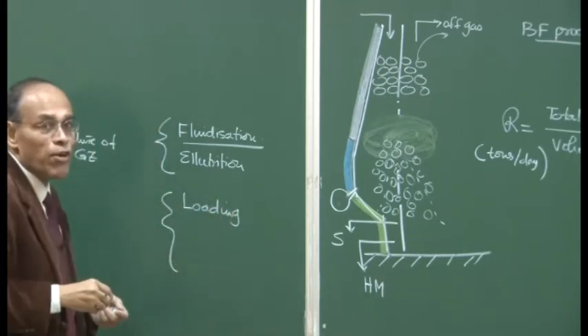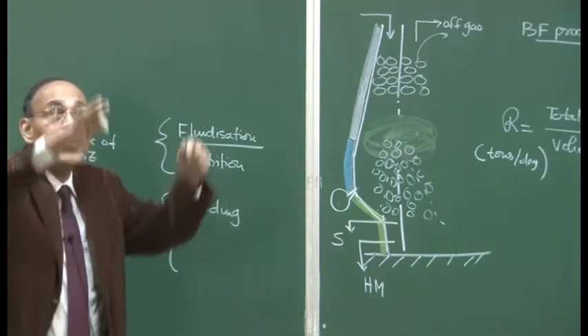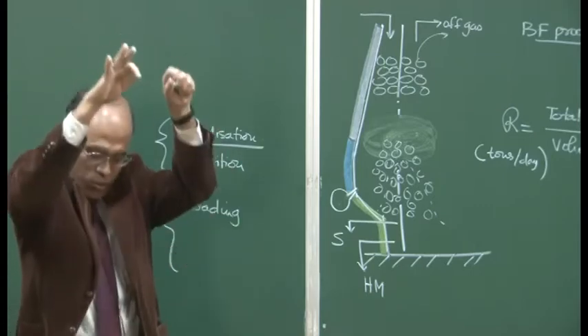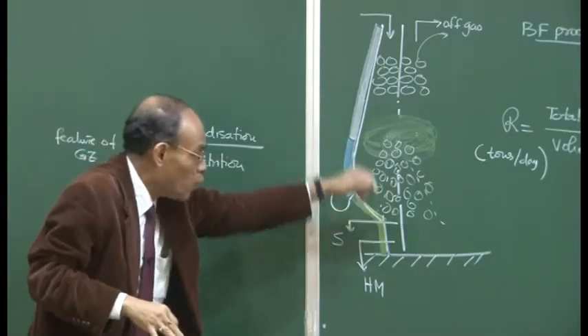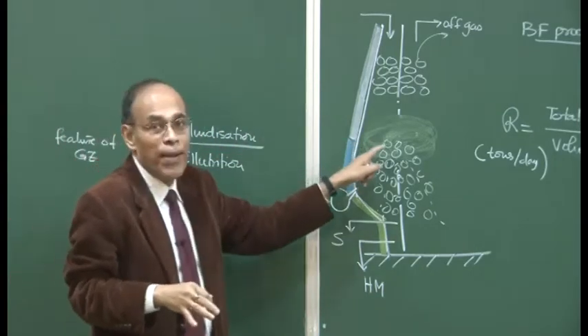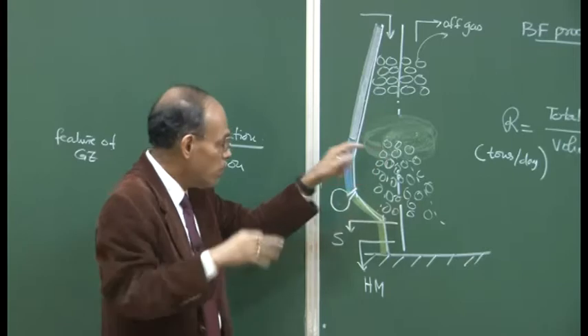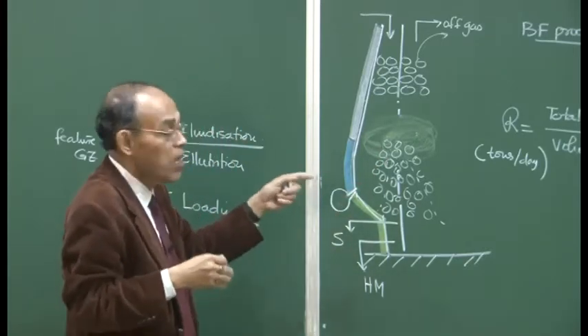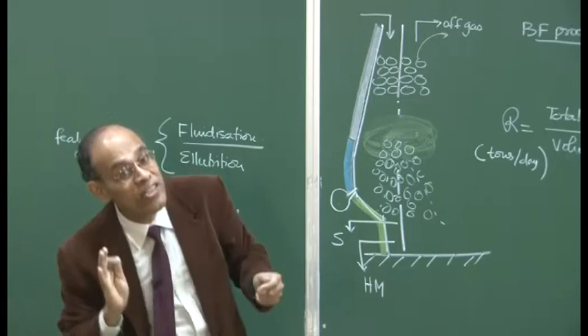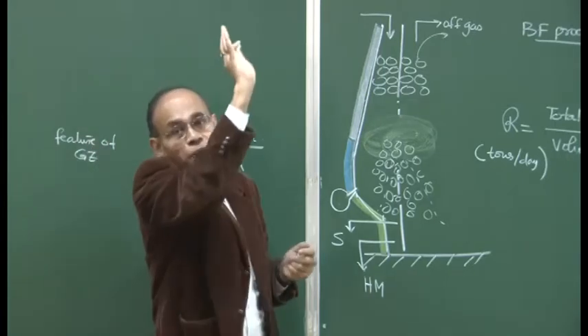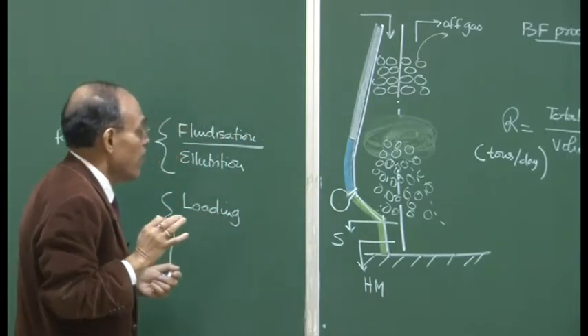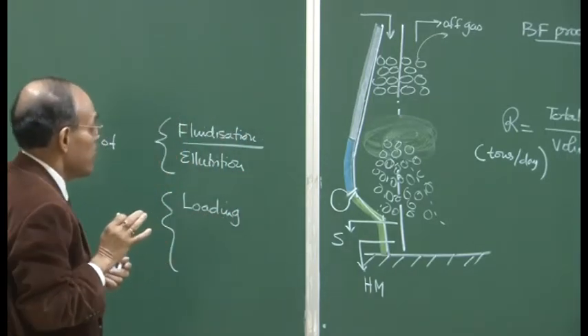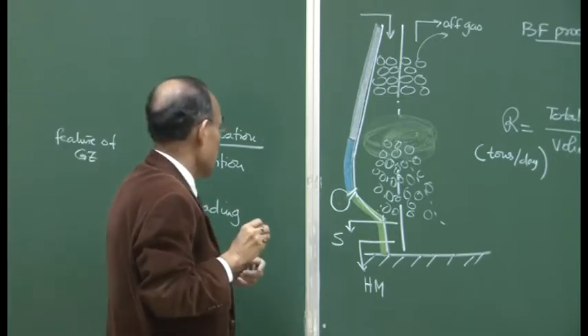If you try to blow a very large amount of gas, there may be a stage when the gravitational force — due to which slag and metal tend to flow — is balanced by the upward drag force of the gas moving upward. As a result, there will be no descent of liquid material, and liquid will cease to flow down and accumulate in the hearth. That phenomenon is known as loading of the furnace.